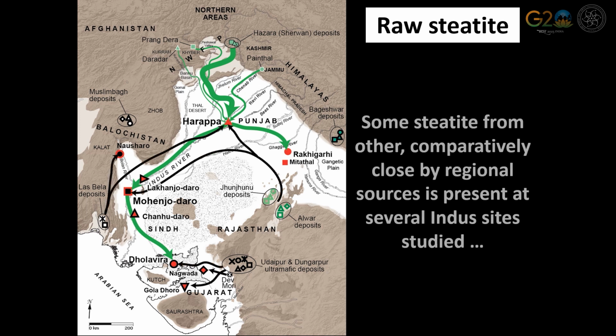Now, a limited amount of steatite from sources in other regions does appear to have been utilized at times. Some of this raw material seems to have been confined to regional acquisition networks, such as steatite from the northern Gujarat, southern Rajasthan region, which was used in limited amounts at sites in Gujarat. At other times, stone was transported longer distances. A few examples of steatite from sources in northern Rajasthan are found at Harappa and Mohenjodaro.